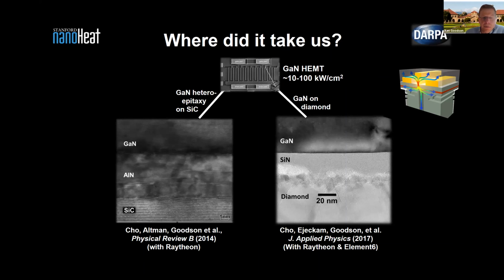And so we were collaborating with Raytheon and Element Six on characterizing. Turns out these interfaces were a big challenge. A lot of the heat would actually bottle up here and not go through the interface very effectively. And so a lot of the optimization work was on improving this interface, and we did a lot of measurements to try and make that work.